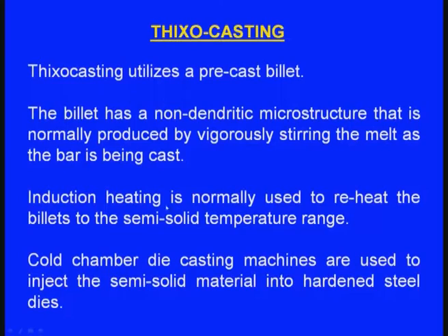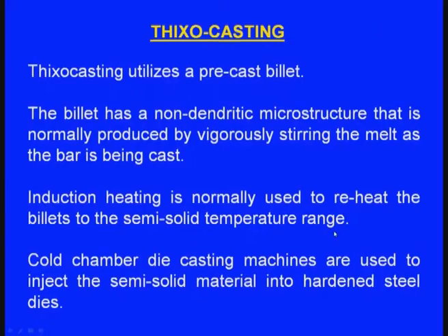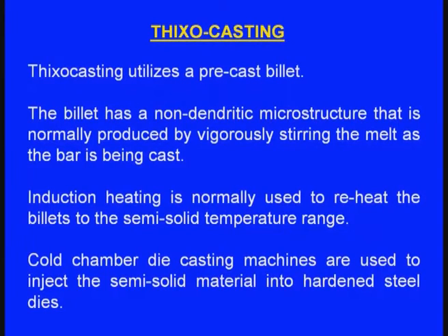Now, we buy this billet and we bring it and we have to cut it into pieces, to the required quantity. Then induction heating is normally used to reheat the billets to the semi-solid temperature range. After cutting these billets, we have to heat them to the semi-solid temperature range, meaning above the solidus temperature but below the liquidus temperature. To such an extent, we have to reheat this billet.